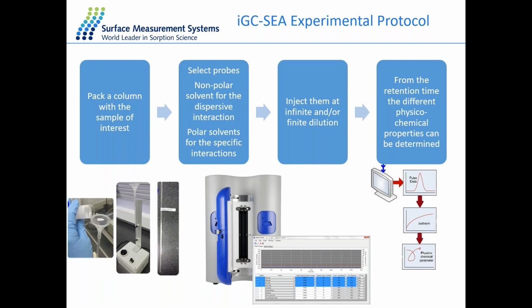So the experimental protocol with the IGC-SEA system is first pack the column with your sample of interest. You would then go ahead and choose some probes for interaction. So if we were measuring specifically for surface energy, we need a mixture of non-polar probes and polar probes. So the non-polar probes give rise to the dispersive interactions, and our polar probes give rise to more specific interactions. We then go ahead and look at the software, and we can choose how to inject these probes. We can either inject them at very small concentrations at infinite dilution or large concentrations. We'll then go ahead and start our experiment, and depending on how the probe interacts with your material, we can obtain different retention times for different probes and understand the physicochemical properties.